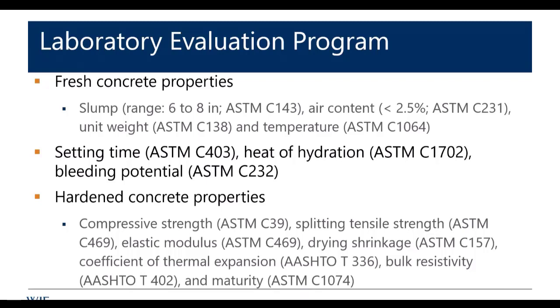We also measured setting times, heat of hydration, bleeding potential, and then hardened concrete properties, including compressive strength, splitting tensile, elastic modulus, drying shrinkage, coefficient of thermal expansion, bulk resistivity, and maturity. So a full range of material testing was done.